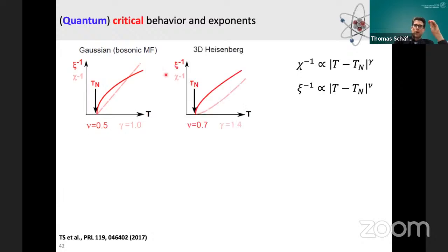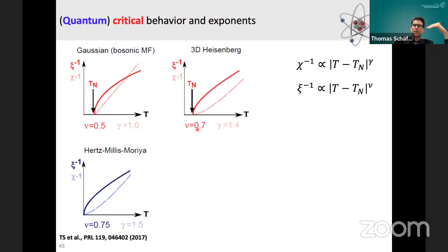The 3D Heisenberg model shows a bit of an alteration of this, namely a gamma of 1.4 and a nu of 0.7. For the quantum critical exponent from weak coupling theory, the so-called Hertz-Millis-Moriya theory, a quantum extension of the Landau-Ginzburg-Wilson framework, we would predict for this universality class a nu of 0.75 and a gamma of 1.5, which is not too different from the Heisenberg exponent.